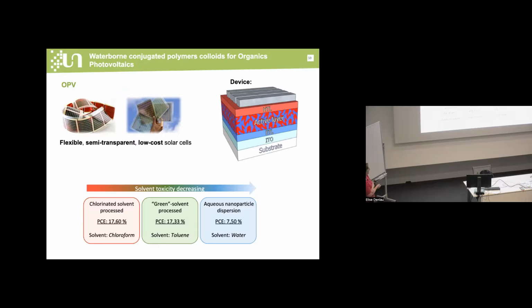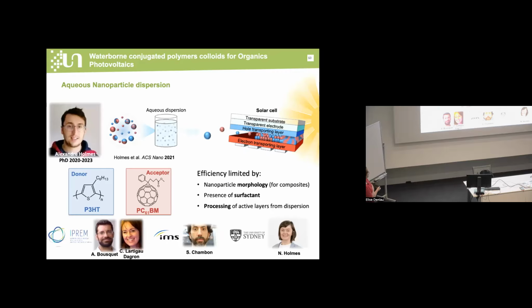So this is why there is a novel way to form the active layer, by elaboration of aqueous nanoparticle dispersions of semiconducting materials. This is the project that we are doing in the PhD of Alexandre Holmes, together with my colleagues Antoine Bousquet and Christine Dagron in Pau, with a collaboration with Sylvain Chambon in Bordeaux and Nathalie Holmes at the University of Sydney. We target nanoparticles of poly-3-hexylthiophene as a donor material, and phenyl-C61-butyric acid methyl ester as an acceptor material. And we want to characterize the morphology of the nanoparticles, and also the effect of the presence of the surfactant on the efficiency of the semiconducting materials at the end.